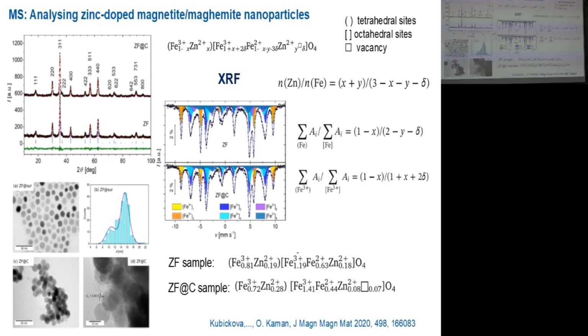We have a third equation. One equation is given by XRF, and two equations are given by this analysis. So three equations for three parameters, and we can resolve the situation. And we can get formulas that will describe the material in detail. And interestingly, this sample, the zinc ferrite prepared by thermal decomposition, was indeed purely stoichiometric zinc-doped magnetite with no vacancies in octahedral sites. The other sample, somehow treated after the preparation, was already partially oxidized to some maghemite.